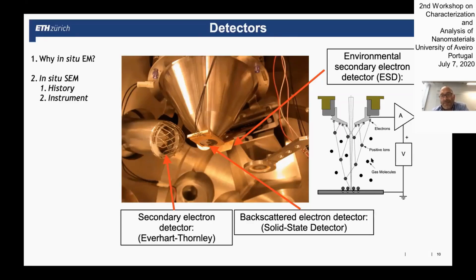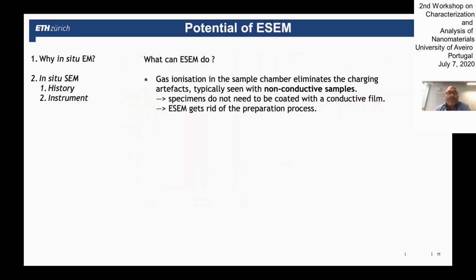In the environmental SEM, you have lots of ions. You can easily charge neutralize the sample. So even if your sample is charging, non-conducting, if you introduce a bit of gas, you can actually study them without putting a coating on. This is really beautiful. So even if you're not interested in any in situ studies, if you want to study a flower or a beetle or whatever, you put something in a microscope, it's normally charging up. You introduce a bit of gas and charging is no more issue.